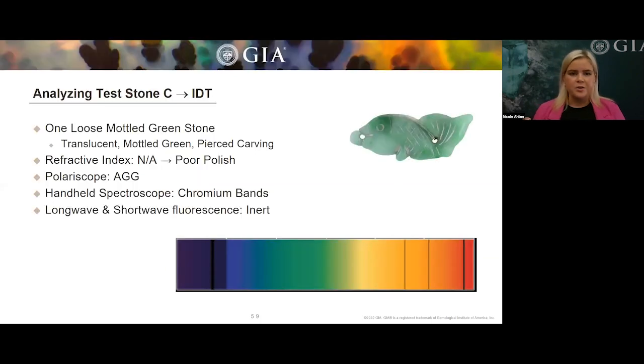Our last test stone is a loose mottled green stone. It's in for an identification report. It's translucent, mottled green in color, and it's a pierced carving. We are unable to get a refractive index due to a poor polish on the surface. We run it under the polariscope and it's an AGG. Then we look in the handheld spectroscope and we got chromium bands, which is great because our stone is green. Then we're going to check fluorescence and it's inert to both long wave and short wave.